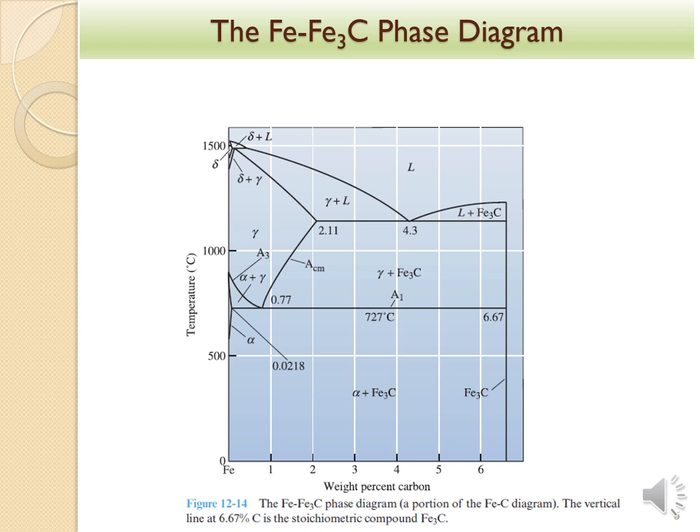The second reaction on this phase diagram is the eutectoid reaction, and eutectoid is from one solid to two solids. On this phase diagram, we have a solid here and a solid at the far left, a very tiny region, and alpha as well is a very tiny region here, so that's solid. And don't forget we have this solid intermetallic compound here. Based on that, for one solid to two solids, I see here at 727 degrees Celsius there is one reaction.